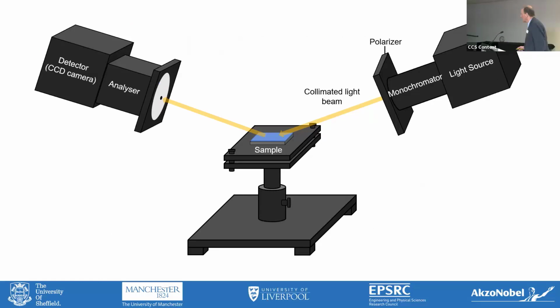It's not a straightforward experimental setup, but if you've got a nice ellipsometer, you can do this experiment. And I should just point out that this is an experiment that's asking a huge amount from an optically based technique. If you want to measure a glass transition temperature in a 10 nanometer film, you're measuring fractions of an angstrom.